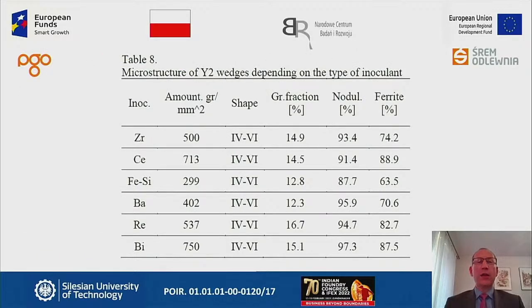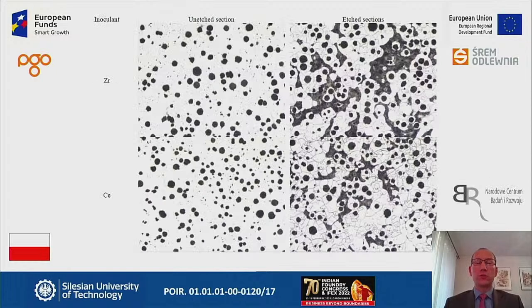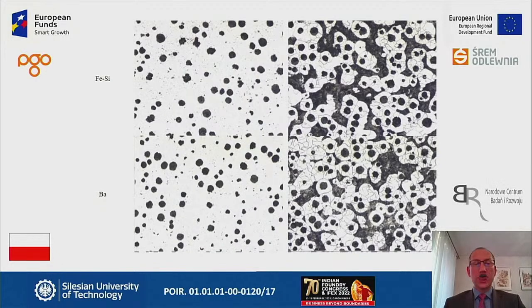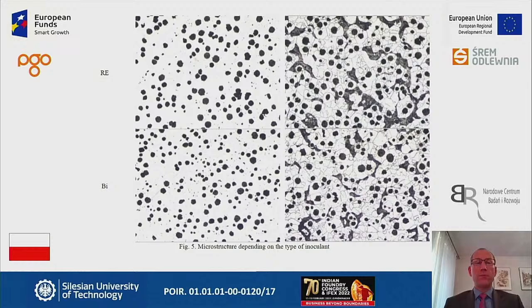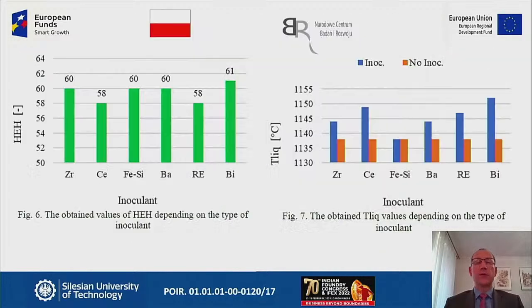Here you can see the microstructure parameters, because of course we focus on the microstructure as well. A few minutes ago I mentioned the chunky graphite problem, the porosity problem, so the microporosity as well. So we've done a lot of microstructure testing or metallographic examinations, and here you can see the selected results for the zirconium based inoculant, cerium based, ferrosilicon, barium, rare earth metals based, and bismuth based inoculants.